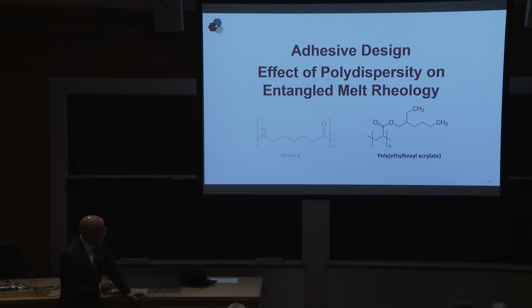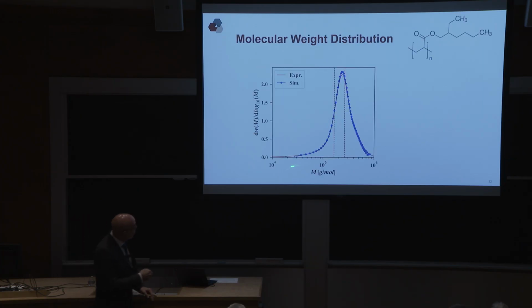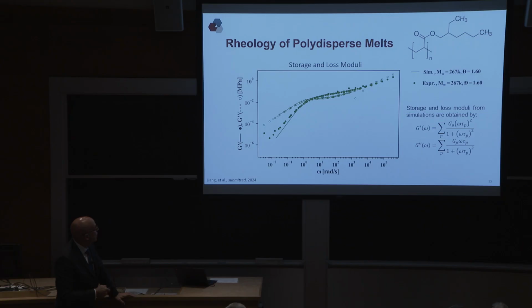But the properties are actually very good. So we had to engineer the molecular weight distribution that we needed to achieve exactly the rheology that we wanted. This was the result at the end of several iterations. And then in here, you see the rheology. That's what they wanted to have, and that's what this design gave them. The lines are simulations, and the points are the experiments. So this seems to work. So we're excited that finally we have something that works for these types of systems.